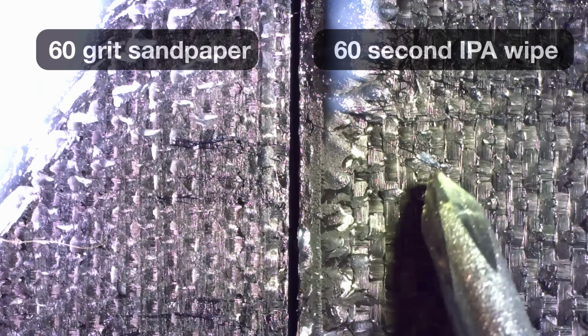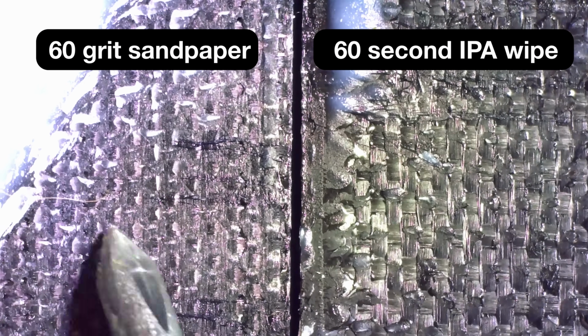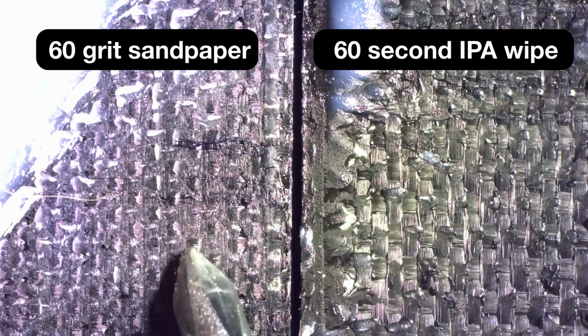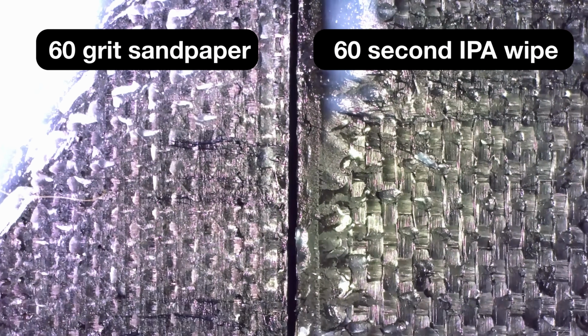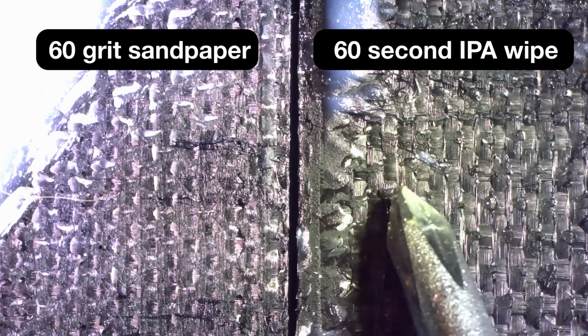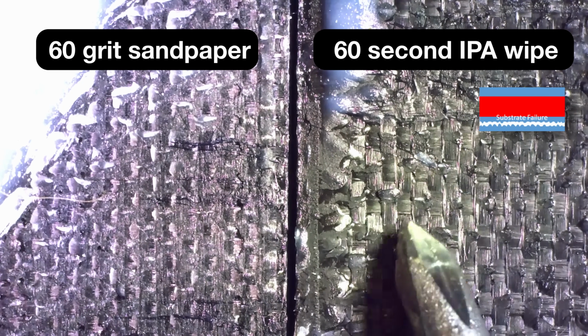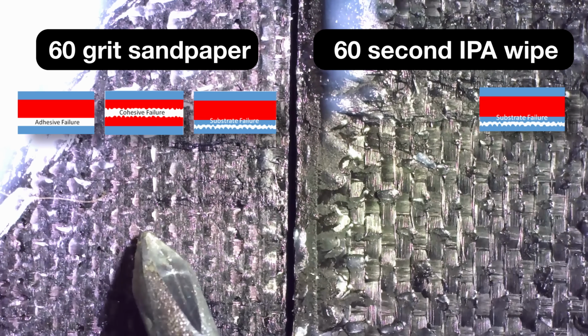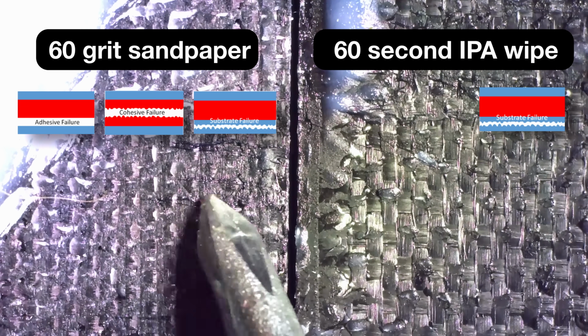Under a microscope, with the 60-second IPA on the right and the 60-grit sandpaper on the left, it's easier to see these two failure modes. For the IPA, we have this total delamination of the resin, so we can see the weave under the substrate, and the 60-grit surface is still rough, which probably contributes to a multimodal failure mode.